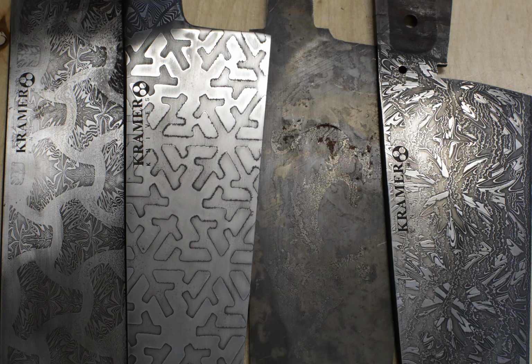And this occurred when my hydraulic press was needing a little bit of maintenance. I don't think it was quite putting out the full power that I thought it was, and this was a lot of surface area to fuse together, and consequently the inserts did not weld completely. They did not squish out completely to the edge. And so when I got to the point of doing the final etch, you can see where the acid attacked the perimeter or the diffusion bond area to the extent where it was pretty clear we couldn't sell this knife. It just wasn't bonded up to the level that we wanted.